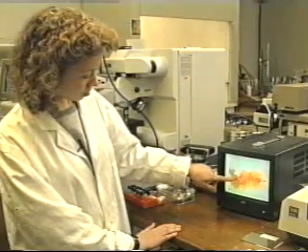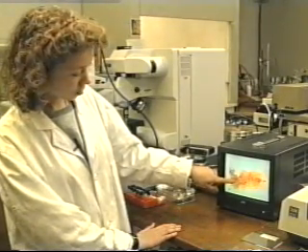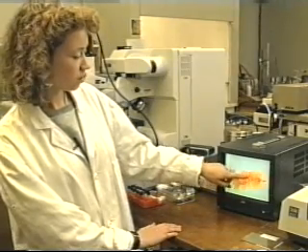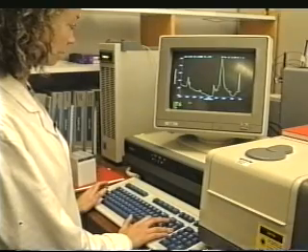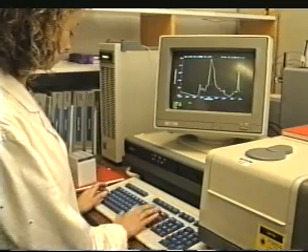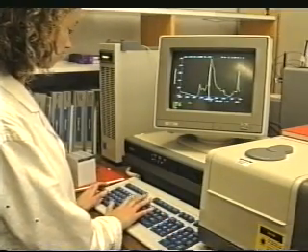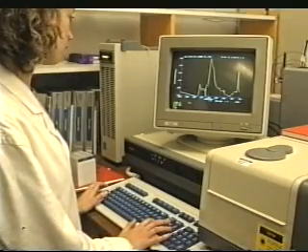Well, here you've got some very dark spots, which is pigment, and very rich red. So we try to avoid those areas and go for the paler bits around the edge here, where there's likely to be more medium. The peaks in the spectrum correspond to varying energies that the organic components need to excite them, and from this we can interpret it to tell us what the medium was.